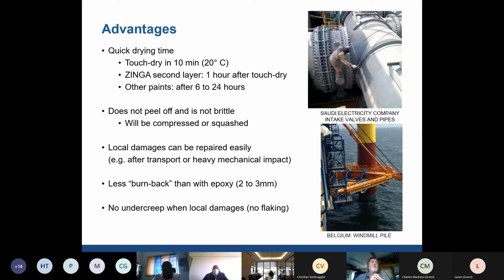With Zinga, it burns off 3 millimeters each side of the weld, which is pretty incredible. And there's no undercreep. It's physically impossible for Zinga to have undercreep corrosion, because with paint you will have. If you have osmotic blistering, when paint gets damaged or porous with age, water can go through the coating to underneath. It starts corroding under the paint, and then you have film undercreep or corrosion undercreep. With Zinga, that's physically impossible because of the voltage flowing from the Zinga into the steel, which flows into every square millimeter of surface area. So it's impossible for you to have undercreep.